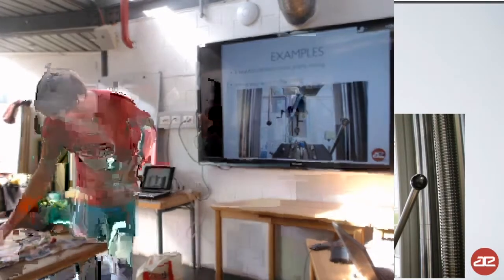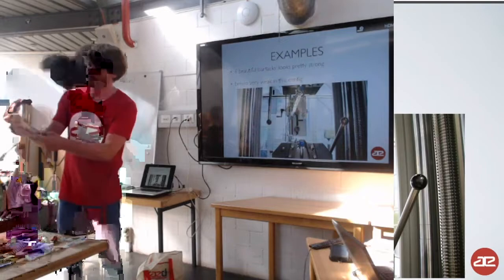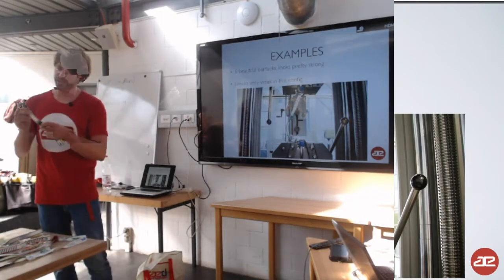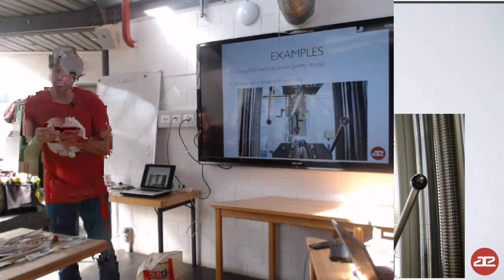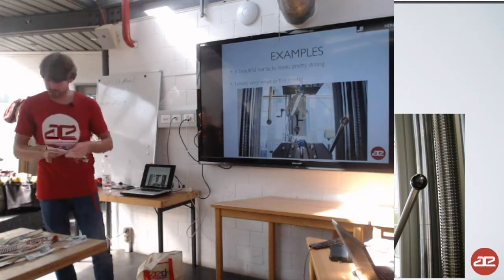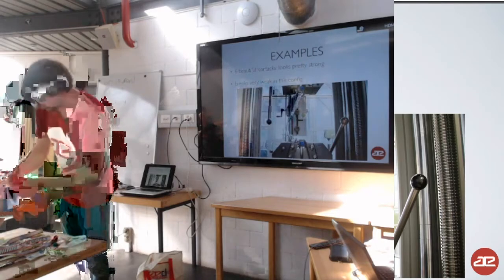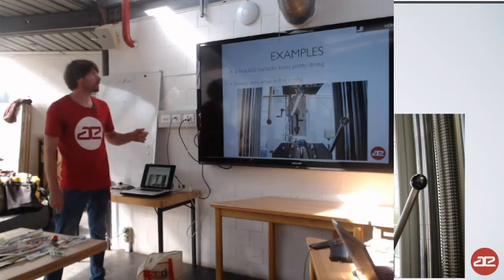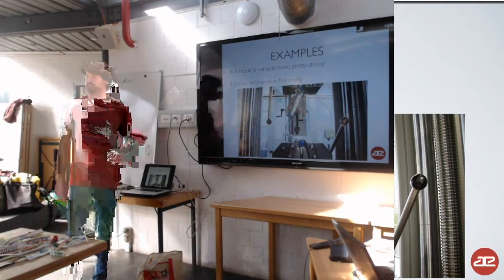But what happens here is not that the webbing itself breaks like it happened in here, but that the bar tacks themselves rip up, because one or maybe more of the parameters that I showed before have been used wrong. These bar tacks didn't look too bad before. They look like this in the first place. I don't think they look too bad, but as we can see, they break at about 65% of the original breaking strength of the webbing.